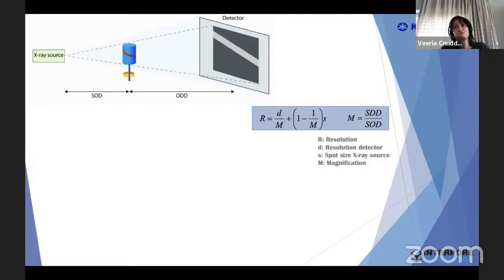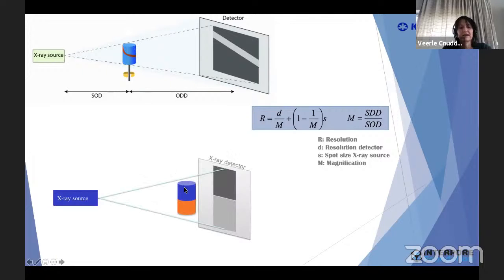And this is then related to the sample size, but also to the composition. Because if you are dealing with a big sample, let's say a rock, what you want is that during rotation it remains in your field of view towards the detector. So if it's a big sample, you will position it much further away from your X-ray source, having a lower magnification and therefore also a lower resolution. Another aspect is that if you are having very dense materials, you typically have to use high energy, and by working at high energy, typically your focal spot also becomes a bit bigger.